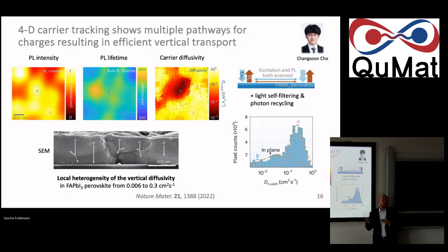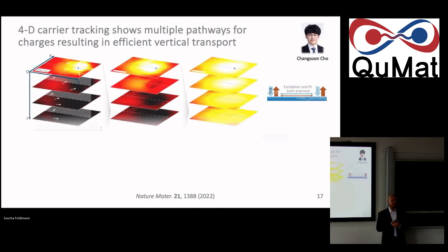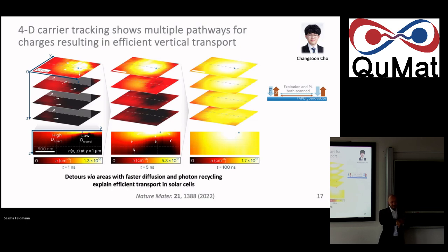Now you can ask, isn't that then very detrimental for our device performance? And the answer is, by modeling now all of this, so four-dimensionally in the X and the Y, and the Z, and time-dependent direction, we can say no. And we can say that also by looking at this. So you excite here locally at the top, of course, but then as 1, as 5, as 10, 100 nanoseconds eventually pass by, you see that even though there are perhaps these hidden grains where you have a harder time to diffuse to the other end or make it to be extracted, there are then other much better suited grains that you might eventually move into through such a photon recycling event or simple drift and diffusion.